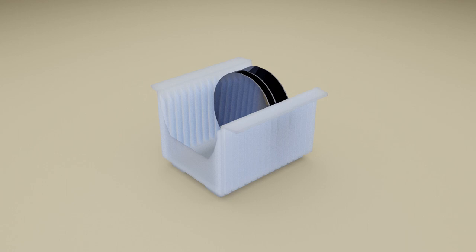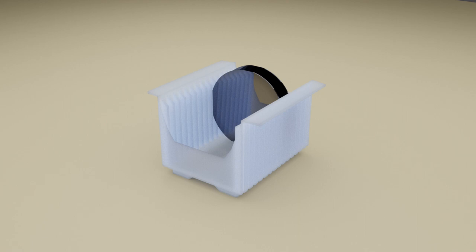The fabrication process started with P-type Czochralski silicon wafers. After standard wafer cleaning, a wet thermal oxidation process was performed at 1100 degrees Celsius, leading to a silicon oxide layer 200 nanometers thick.